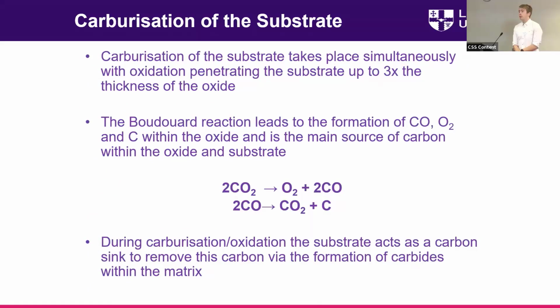The carburisation of the substrate takes place simultaneously with the oxidation of the steel, and it can penetrate up to 3 times the thickness of the oxide. And due to the Boudouard reaction, which can be seen there, oxygen, carbon dioxide, carbon monoxide and carbon are all potentially present. During the carburisation of the steel, the bulk metal is able to act as a carbon sink, removing this carbon, which leads to the formation of carbides within the material.